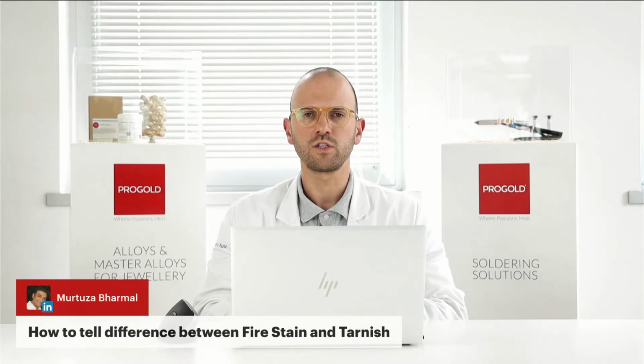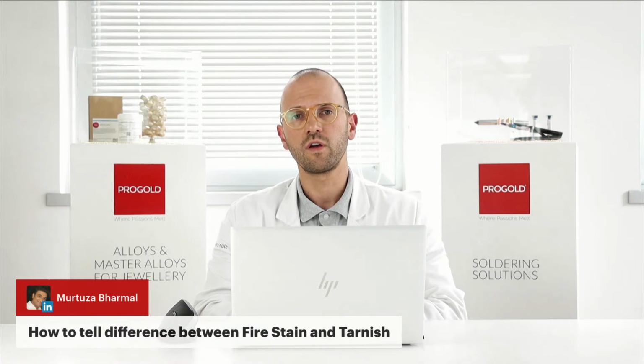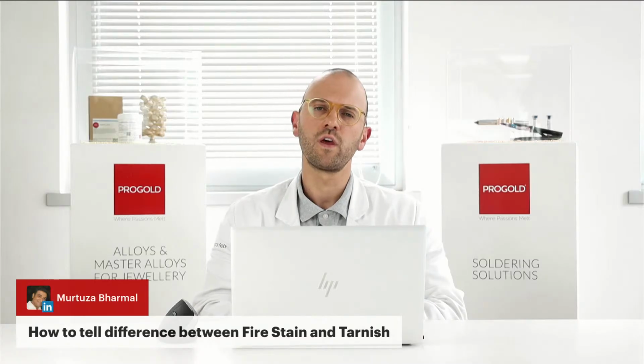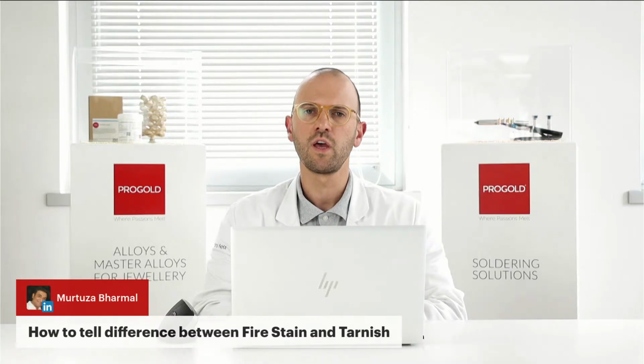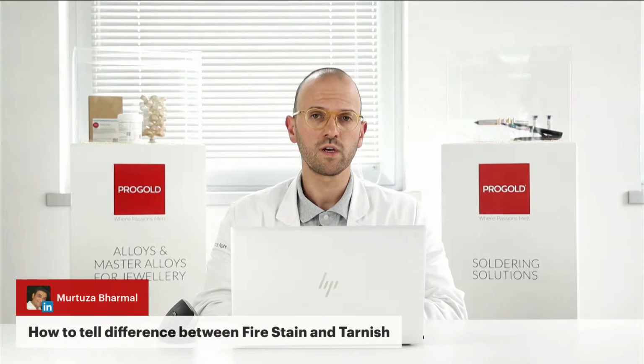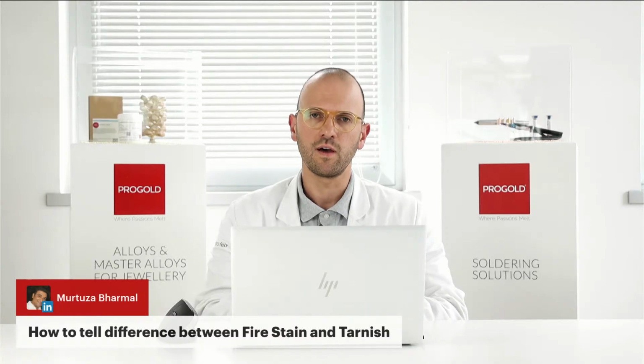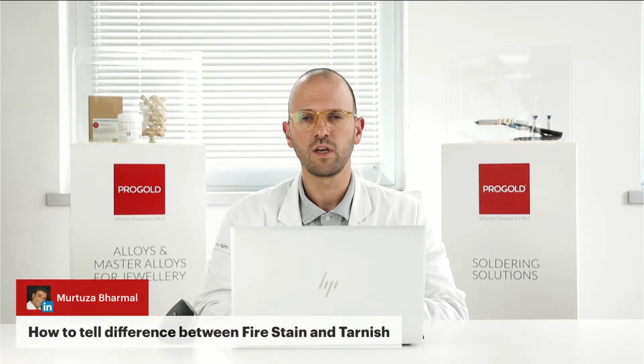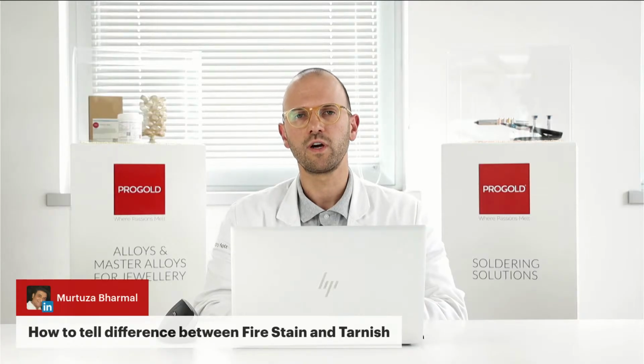In the case of tarnish, the defect is a little bit different, and stains on the surface could appear even after a long period of time. So the first difference is the timing in which the defect appears. In the case of Firestain, the defect appears during the solidification, and after polishing you could easily identify it. In the case of tarnish, you could recognize it also over time.